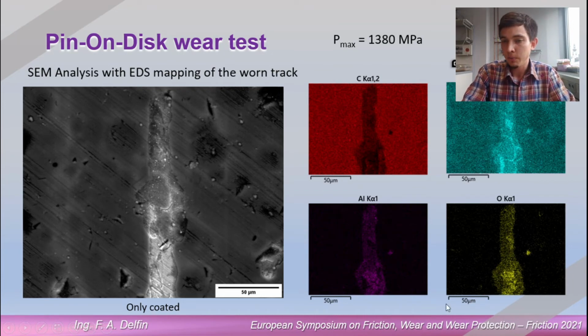And we also saw in the inner part of the track, in this delamination zone, the signals of aluminum and oxygen. So here the alumina of the counterpart is starting to leave some debris only in this attachment area because of how this works.